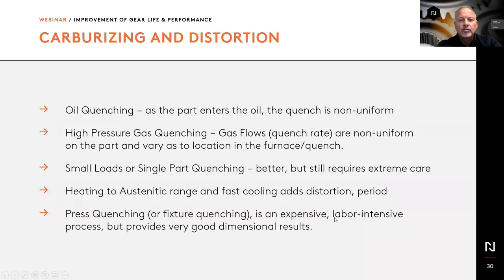In carburizing, we must cool very fast, which is quenching. In oil quenching, the part basically is lowered into the oil. This means non-uniform cooling by definition of how the part moves. In high pressure gas quenching, the gases do not act perfectly like liquids do. So we use very high pressures in order to mimic a liquid, but it is very hard to get even flows of gases around the parts, especially in more dense loads. So people have moved to different techniques to try to get rid of some of these problems, like single part or single layer gas quenching. This is much better, but it's still not perfect.